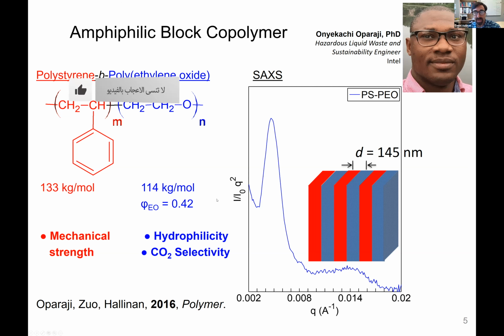We did X-ray scattering, which tells you about the characteristic domain size, the periodicity of the block copolymer, of the lamellae. This primary peak tells us about that characteristic size, and the spacing of the primary and secondary peak tell us that it is lamellar.